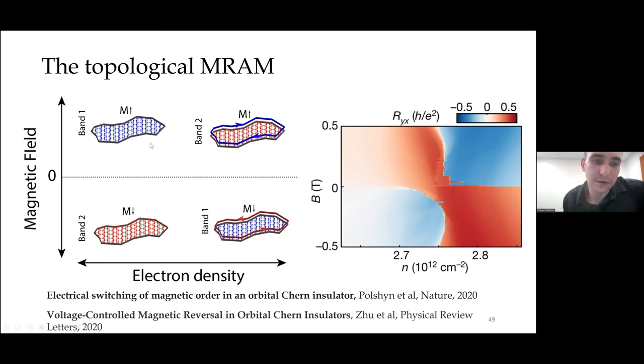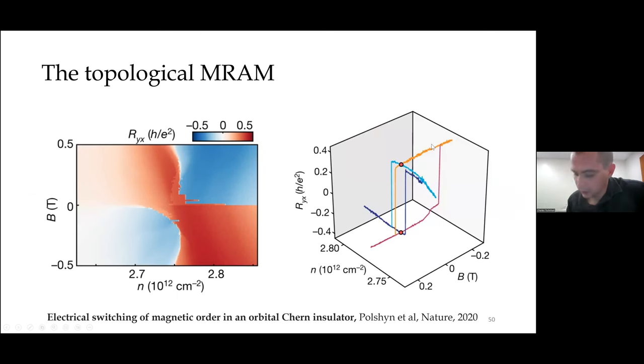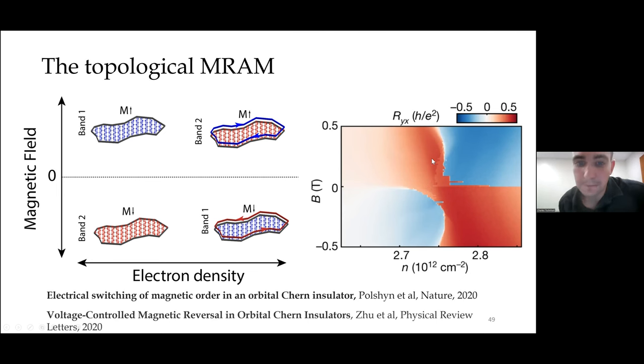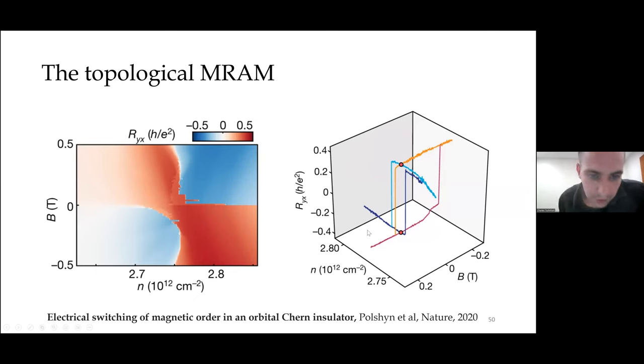So if you have a ground state that is spin up, you populate your chiral edge states, you switch the sign of the magnetization, you will end up with the spin down state as the ground state. And we can see that in the anomalous Hall resistance as a function of electron density and as a function of magnetic field. So on this side, we see this positive anomalous Hall resistance change to a negative anomalous Hall resistance across this boundary where the magnetization passes through zero. This is also a first order phase transition.